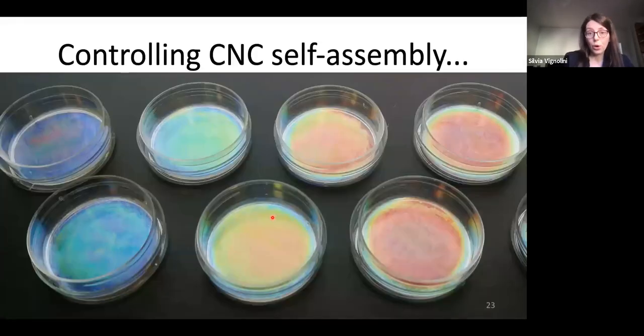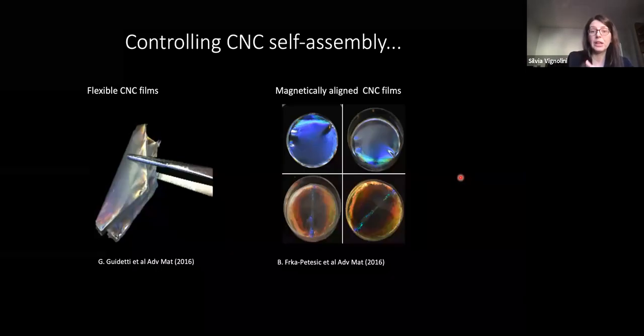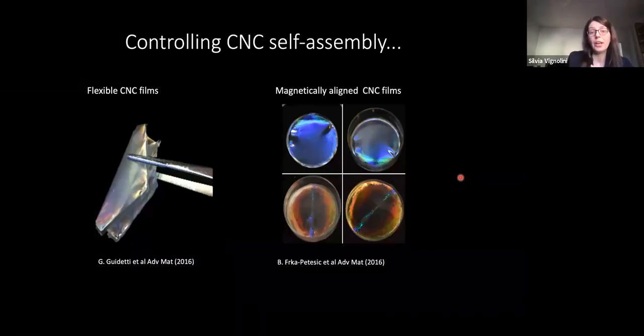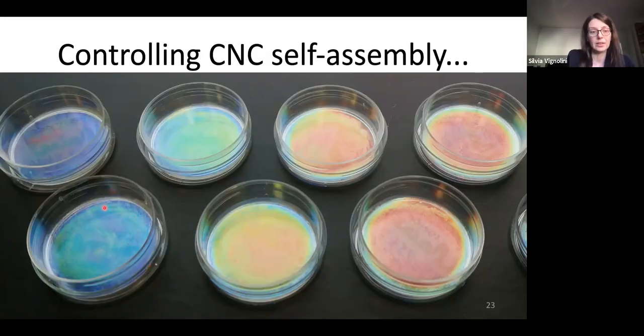So once you know how to control it, and once you know how to properly manage the self-assembly properties, you can really change the color in the entire visible spectrum. You can even reach the ultraviolet and the infrared region. And you can really play also with the self-assembly by changing the composition, by adding other dopants inside the film. These differently colored films are just obtained starting from exactly the same material, cellulose, and then we add some salt. The only thing that we do is add really a little bit of salt, a millimolar amount, so that the interaction within these cellulose nanocrystals, that we call CNC, changes, and then we can tune this coloration.